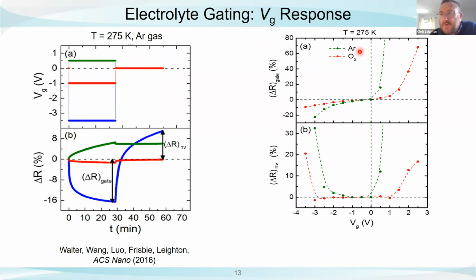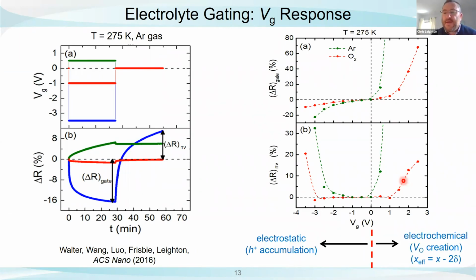This is both in argon, an inert gas, and now also in oxygen. And the most striking thing I think about this is the massive asymmetry between positive and negative bias. So in particular, a positive bias, we can get very large gate-induced changes. They actually go way off the scale of this plot, but they're almost entirely non-volatile. And when we put the device in oxygen, we can strongly suppress the effect. This isn't proof. I'm going to show you more proof later. But this is a strong hint that what's going on at positive voltages is electrochemical. We form oxygen vacancies and thereby control transport and magnetism.